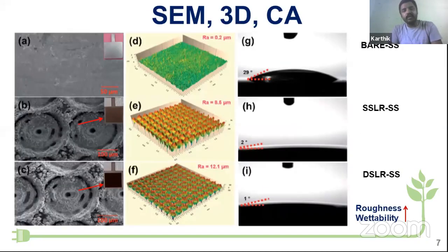This slide shows the SEM, 3D, and the contact angle of the bare, single side, and double side laser rusted stainless steel. Figure A corresponds to the bare stainless steel, which consists of a smooth surface with gray silver color. Whereas when the pre-cleaned stainless steel is irradiated on single side, the perfect honeycomb texture has been drawn over the substrate, which is confirmed visually through the formation of a light brown colored layer, which is nothing but rust. That is, the main constituent present in the stainless steel is Fe, which undergoes oxidation to its oxides. When the substrate is irradiated on both sides, the intensity of the brown color increases. That is, a dark brown rust layer is formed over the substrate, which confirms that a thick or dense rust layer of oxides of iron, nickel, and chromium is formed over the surface.